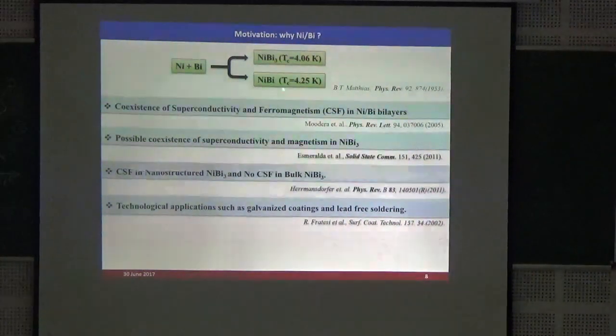So apart from this superconductivity, in 2005, Moodera et al. reported that there is a coexistence of ferromagnetism also in the nickel bismuth bilayers, which was also confirmed. This was also reported in the case of one of the stable phases, NiBi3, in 2011, and Hermansdorfer et al. reported that in the case of nanostructured NiBi3, they observed CSF. However, in the same paper, they reported that bulk NiBi3 doesn't show CSF. Whether NiBi3 shows coexistence or not is still under debate, so it needs further exploration.